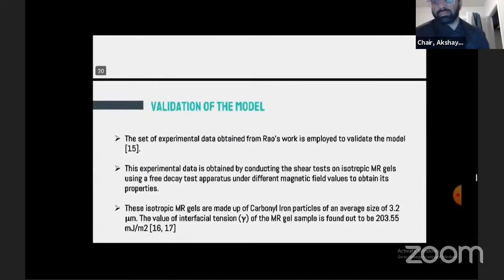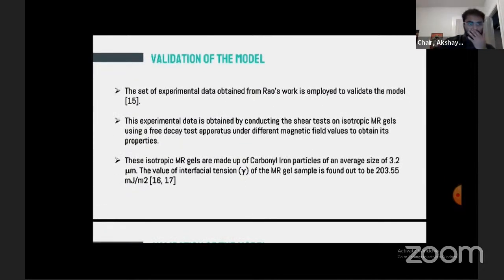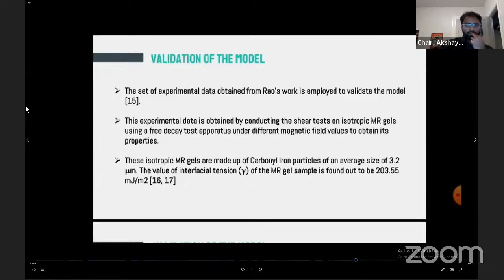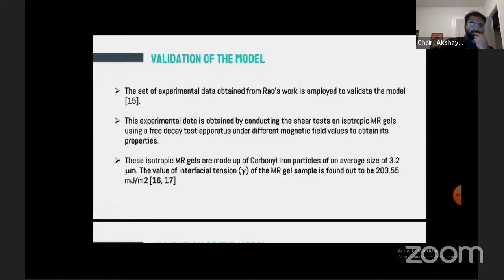This model is validated with a set of data obtained from previous work. This experimental data is conducted by performing the shear test on isotropic elastomers using a free decay test apparatus and at different magnetic field values to obtain its properties. The isotropic gels are made up of carbonyl iron particles with an average size of 3.2 micrometer. The interfacial tension of the elastomer sample is found to be 203.55 millijoules per meter square.